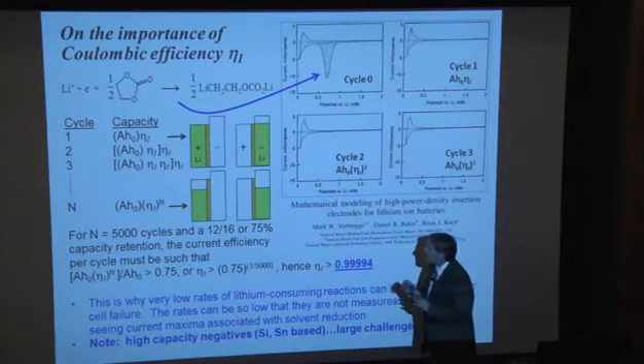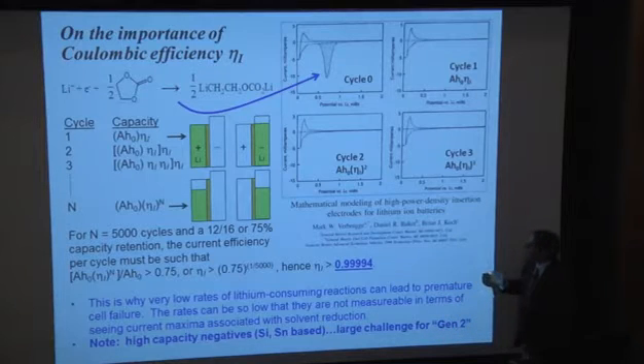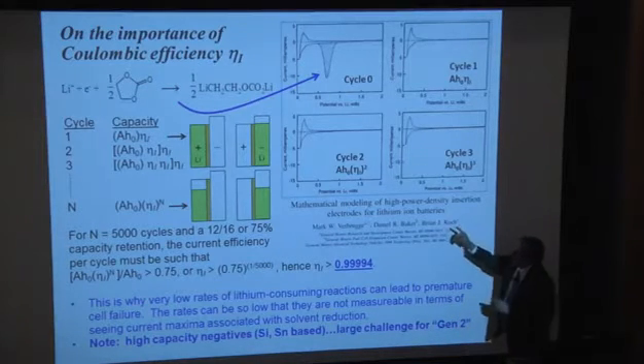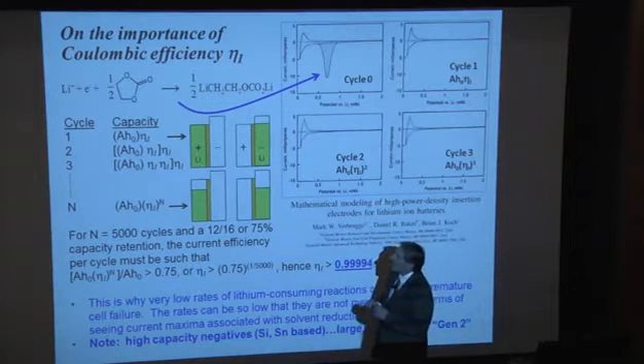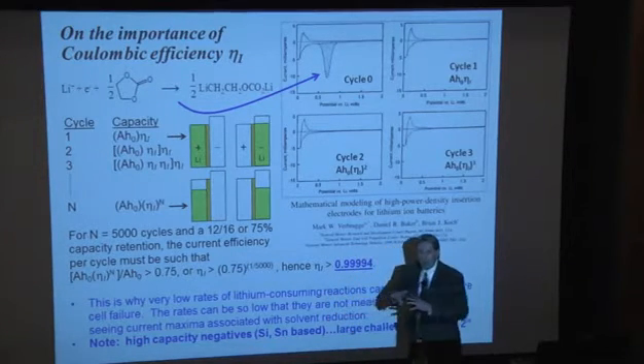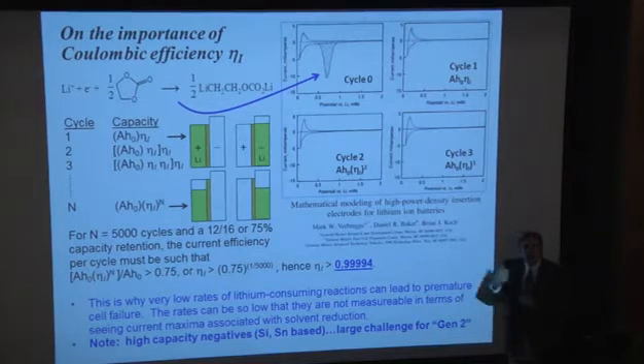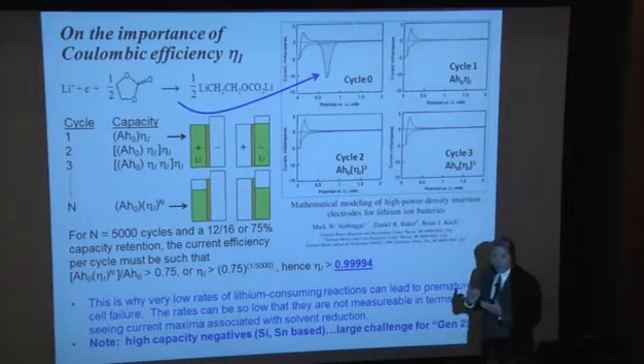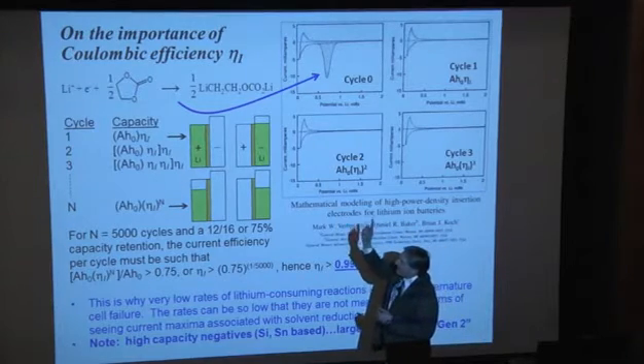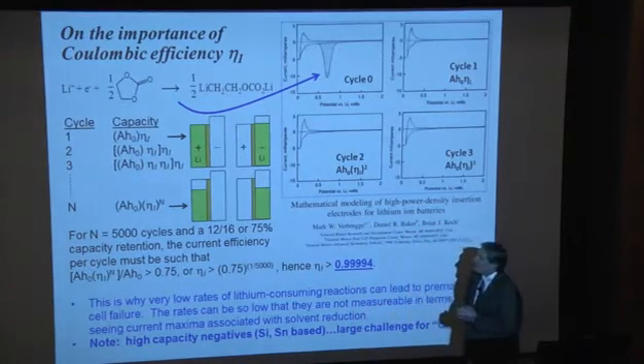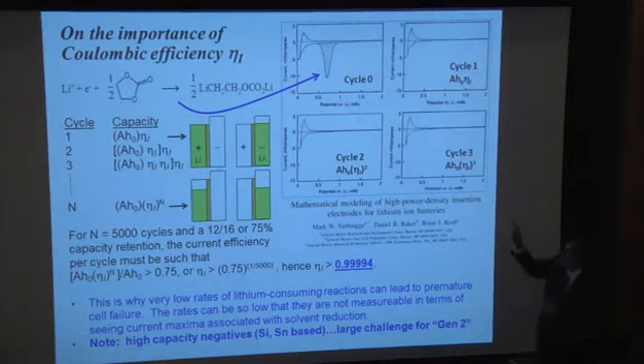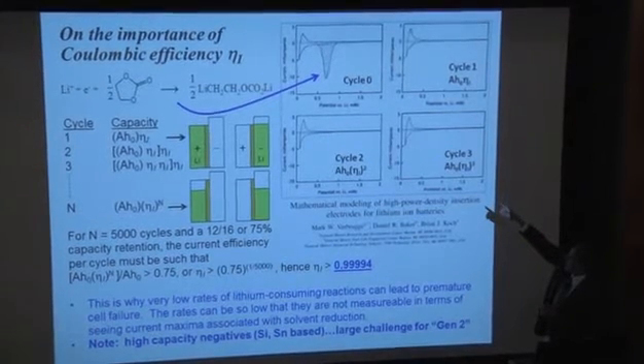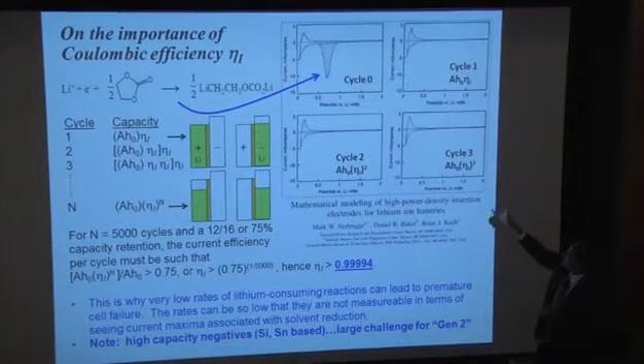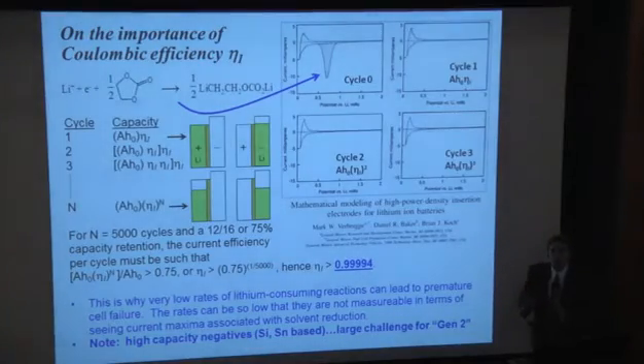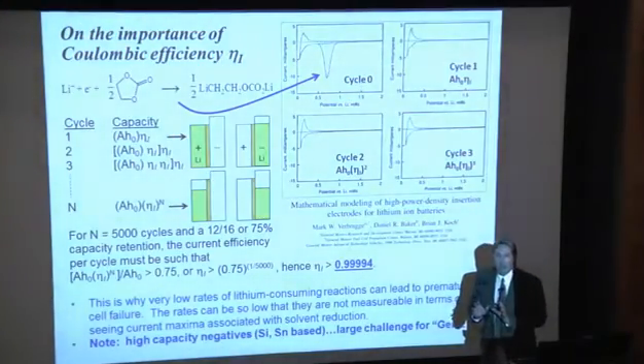Now, that's kind of part of the story. And this comes from the same reference as before, but after you start forming the carbonate as an inorganic inner layer to form this film over the surface, you start generating these lithium adducts afterwards, these organic layers, and by FTIR, the general reaction that is accepted as most common is listed up there. So that reaction is actually occurring at that same voltage in what I've called cycle 0, where we have the conditioning, but cycle 1, cycle 2, and cycle 3, it's still occurring. Just at such a low rate, it's hard to measure it. The current efficiency is very, very high.